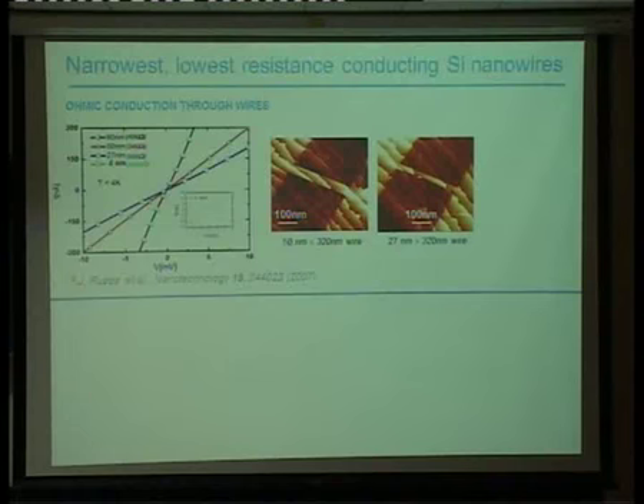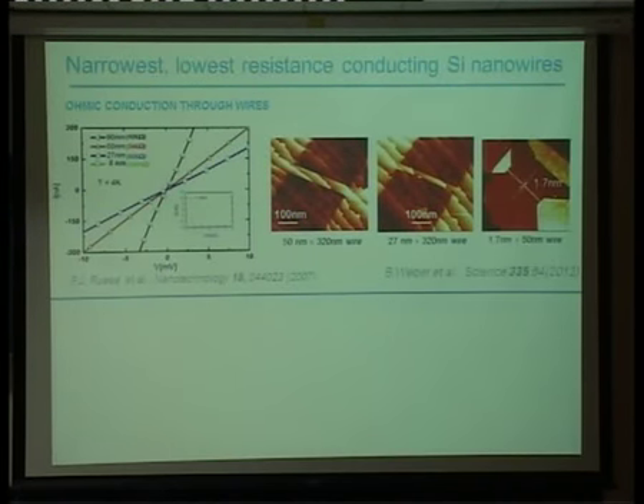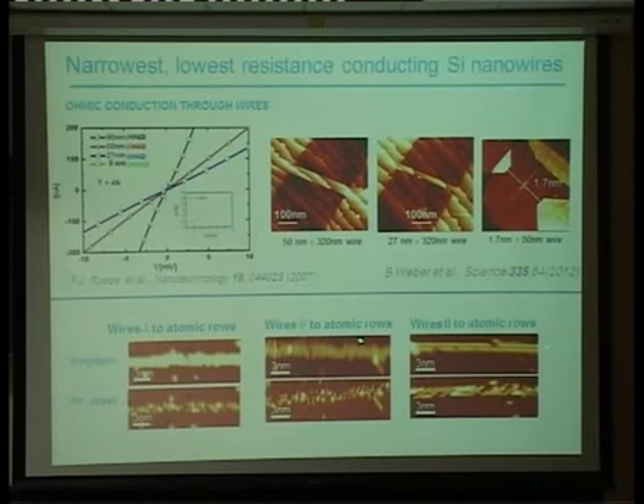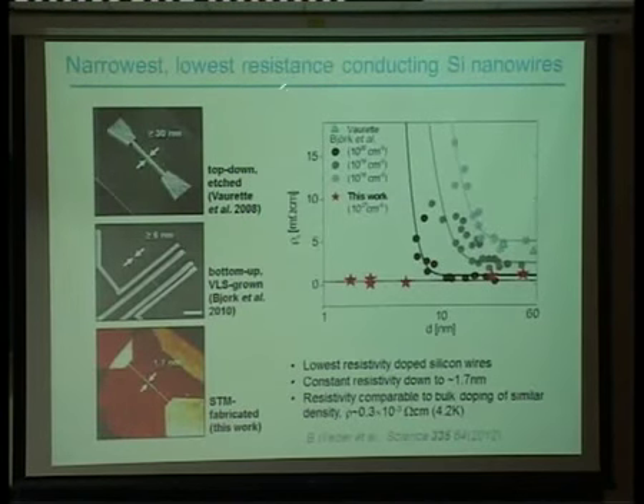So now what we did was we basically went to make these wires thinner and thinner. And you can go all the way down essentially now to where the wires are 2 dimers wide, so literally 4 silicon atoms wide. And you start to see now that the chemistry again comes into play. The phosphine likes to dissociate along the dimer row and not perpendicular to the dimer row. And as a consequence, you get lower resistivity in these structures where you basically pattern the wires along the dimer row.